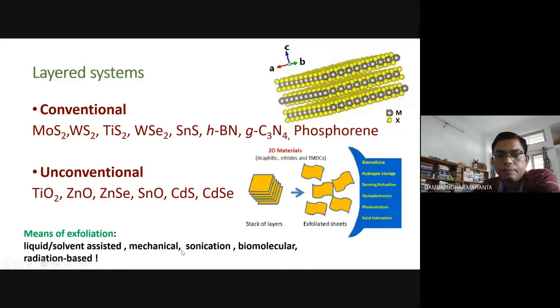Another is mechanical exfoliation, peeling of the surface, or maybe you can have a rotating plate, and beneath it you put your sample, the stack of layered material, and slowly you make it come down, and the surface will be taken out one by one. So this is very risky. For wide-area layered materials, it is difficult to make. Sonication is a must, especially when you are considering liquid solvent assisted exfoliation.